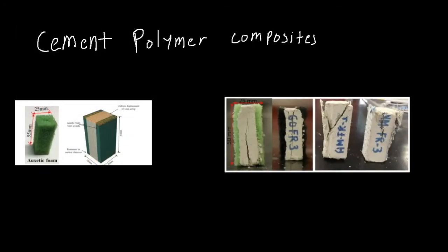So let's end by talking about some applications of a negative Poisson's ratio. Polymer foams with negative Poisson's ratios have been investigated for a range of applications towards energy dissipation or redirection. The reason for this is when an auxetic foam material is compressed, it responds by becoming denser, as we mentioned before. So the result is, rather than dissipating energy to other areas of a solid, the auxetic material causes the energy density to increase. And looking at researchers at Queensland University of Technology, they investigated the application of this phenomenon to cementitious composites, or cement composites.